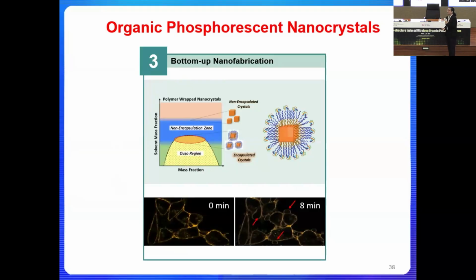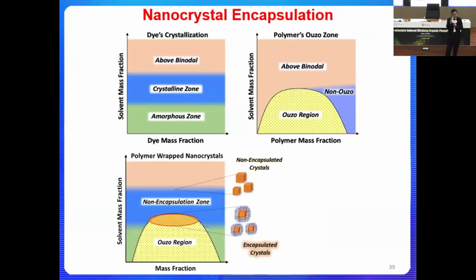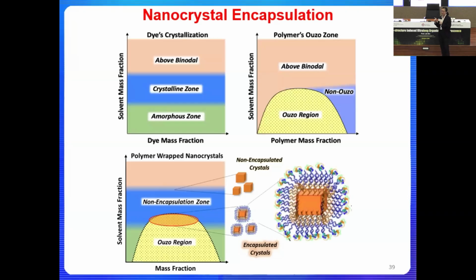And at the same time, we want to make sure these organic molecules will recrystallize, right? So we also need to look into which solvent combination is just good for this molecule to recrystallize concurrently. All right. So if we overlay the recrystallization zone and also the nanoparticle formation zone, for all the combinations in terms of solvent and molecular mass ratio, there's only this tiny region. If you operate in this tiny region in terms of concentration and solvent combination, you stand a chance to get the particle. So you have to work on two phase diagrams, one for nanoparticle formation, one for crystallization. And you will be able to identify this zone that will give you small sized nanoparticles that are crystals in the aqueous media. And then we can functionalize the surface to make it highly specific for biomedical applications.